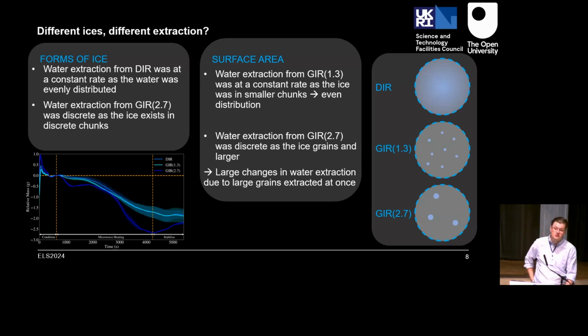For the surface area, actually, we found something I wasn't expecting. For the smaller grains of ice, you'd expect higher surface area, more in contact with the simulant, and therefore you'd expect a higher water loss going on. But actually what we found was the other way around. The larger grains were producing a higher water loss.